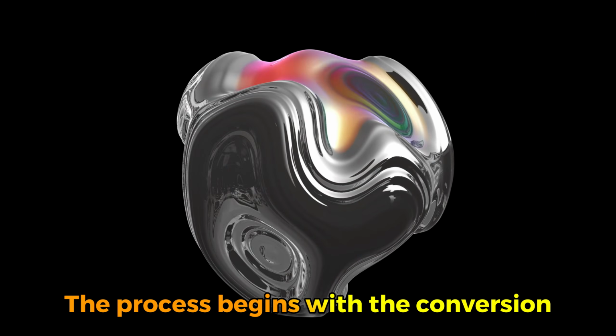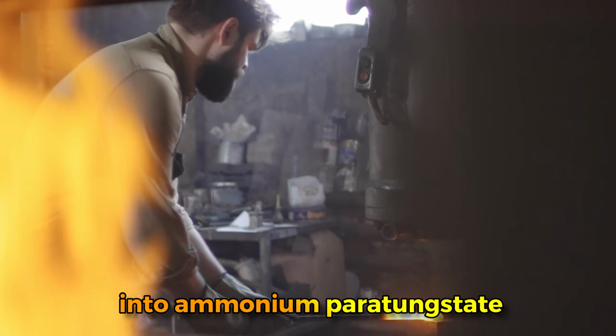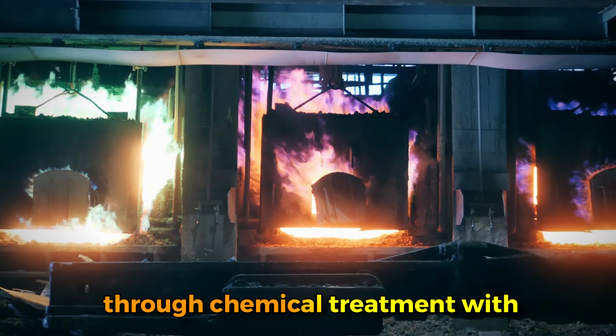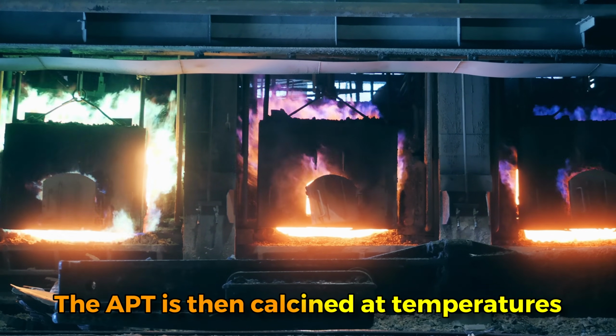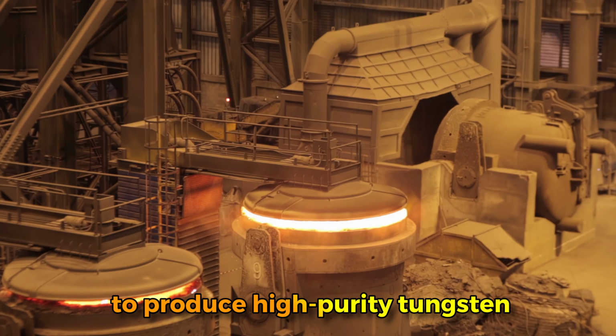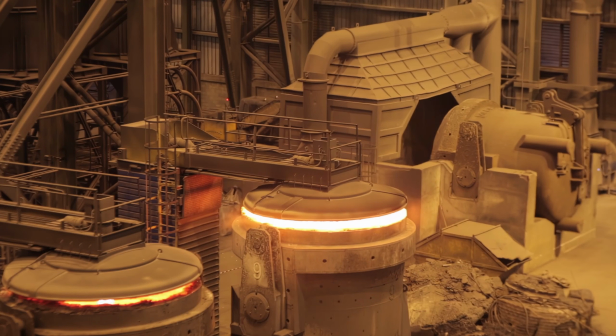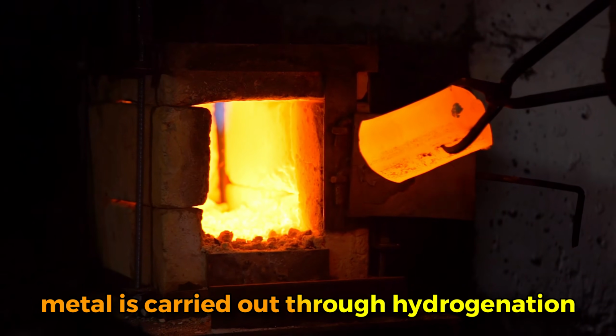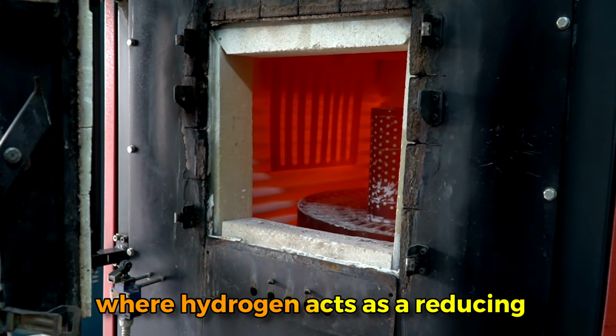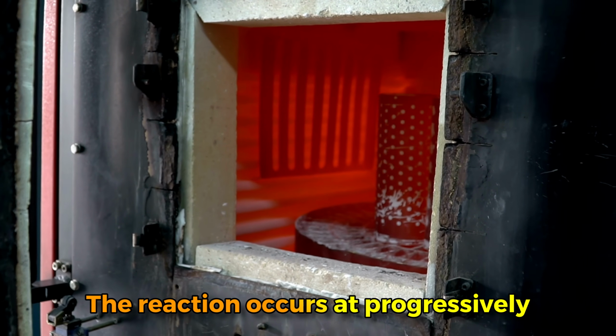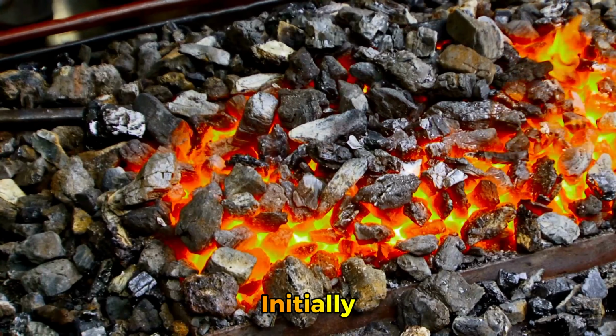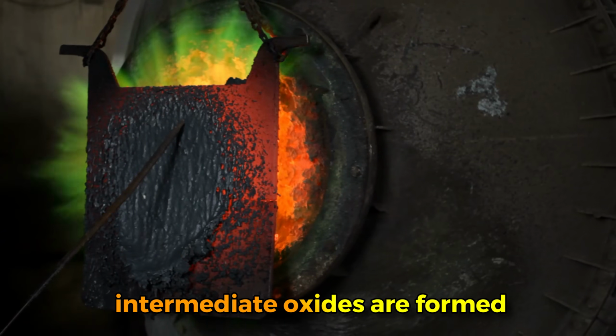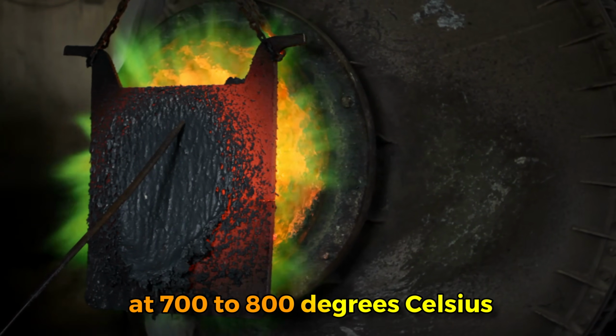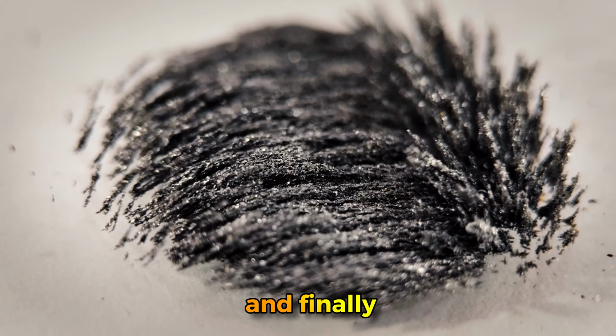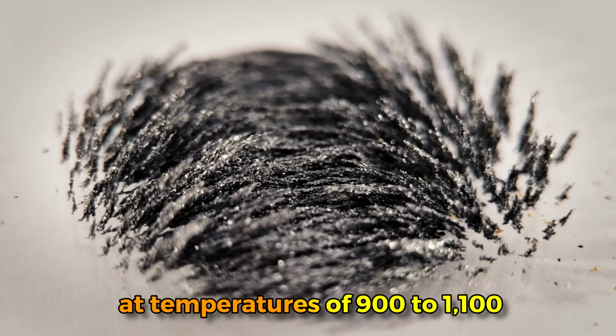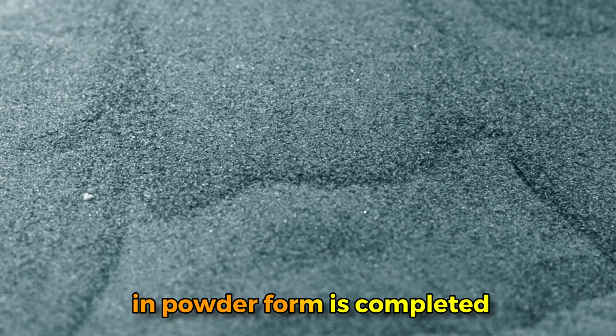The process begins with the conversion of the concentrate, WO3, into ammonium paratungstate, APT, through chemical treatment with ammonia. The APT is then calcined at temperatures of 600 to 800 degrees Celsius to produce high-purity tungsten oxide, WO3. The reduction of the oxide to metal is carried out through hydrogenation, a staged process in tubular furnaces where hydrogen acts as a reducing agent. The reaction occurs at progressively higher temperatures. Initially, at 500 to 600 degrees Celsius, intermediate oxides are formed. Then, at 700 to 800 degrees Celsius, WO2 is obtained, and finally, at temperatures of 900 to 1100 degrees Celsius, reduction to metallic tungsten in powder form is completed.